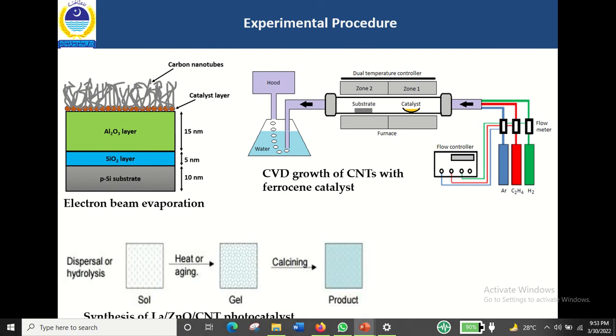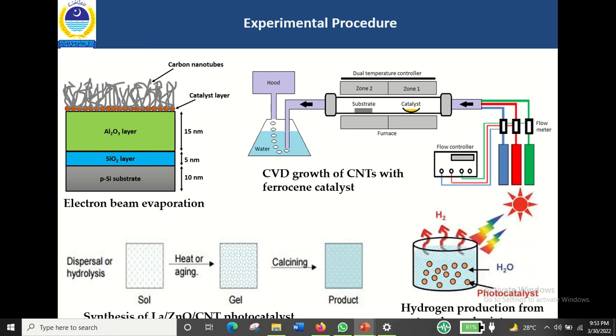And then these carbon nanotubes, along with the lanthanum, were used in a sol-gel method to prepare a composite photocatalyst of lanthanum ZnO CNT. And then this photocatalyst, along with the pristine ZnO, was used for the production of hydrogen from the water glycerol mix solution under the visible light from the sun.